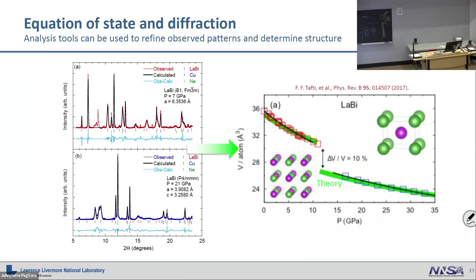So here's just an example of what you get out. You get that 2D diffraction pattern that I showed you on the previous slide, and then that gets integrated out as a function of 2 theta to give you what you would see as a conventional diffraction pattern. More and more people are starting at the synchrotron to analyze that 2D pattern instead of going through all of this integration, because you're losing information by collapsing all those angles down to just a 2 theta. So you want a 2 theta and a phi, but I don't know how to do that, so I'm not going to tell you how to do this. So once you collapse this down, there's some subtleties to that about how you integrate around the rings and how you mask that Adam talked about. But once you do that, the analysis is fairly straightforward, and it's the same as you would do with a lab source.